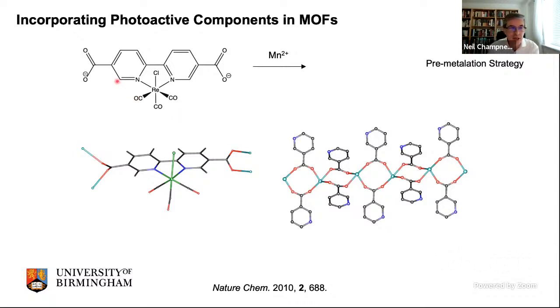So all we're doing here is making this into a dicarboxylate. We put these carboxylate groups on either end of our bipyridine molecule, and we now have a simple dicarboxylate which we can use to make MOFs. So we take this and react it with manganese 2+. You can use other metals, but this is just where we started. The manganese binds to the carboxylate. You make manganese carboxylate chains that you can see here. And then off the side of the chains are the bipyridine ligands, which are binding the rhenium complex.